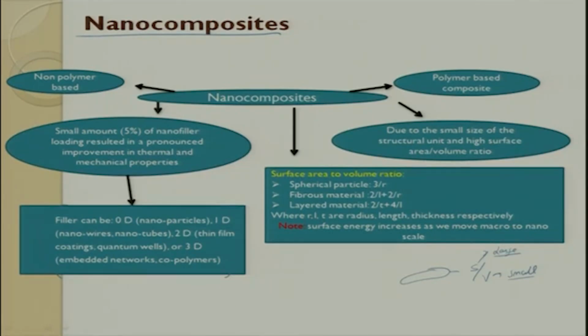So what is the processing difficulty with this nano composite? Nanoparticles have a large amount of surface charges. The moment you have large amount of surface charges, they quickly get agglomerated. Once agglomerated, the functional property is not uniformly distributed across the matrix, so you will have chunks of nanoparticles loaded at a few spots, and some areas will be exclusively polymer.